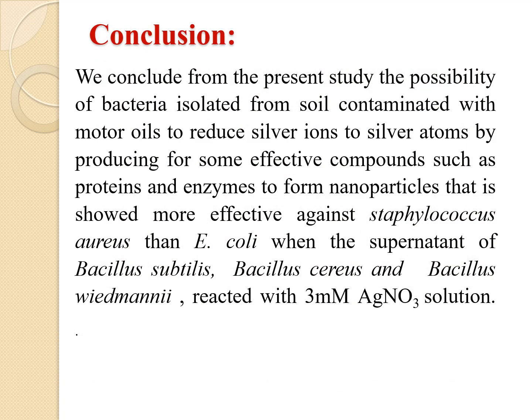We conclude from this study the possibility of bacteria isolated from soil contaminated with motor oil to reduce silver ion to silver atom by producing some compounds such as proteins and enzymes to form nanoparticles. That showed more effectiveness against Staphylococcus aureus than E. coli when the supernatant of Bacillus subtilis, Bacillus cereus, and Bacillus wiedmannii reacted with 3 millimolar AgNO3.